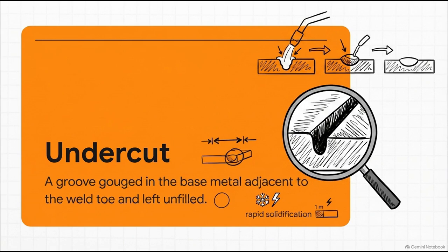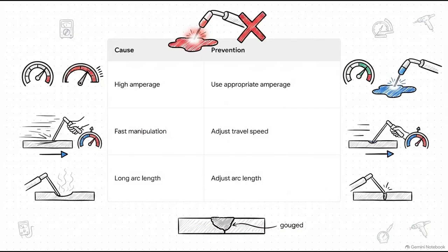Next up is the undercut. Now, unlike porosity, which is an internal bubble, an undercut is a physical scar right on the outside of the metal. It basically looks like a groove gouged into the parent metal right along the edge, or what we call the toe of the weld, and it's left completely unfilled by the filler material. It usually happens when the rapid solidification of the metal prevents it from wetting back properly into the groove it just melted.